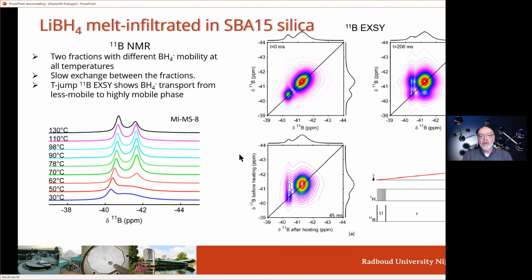Okay, so we also did two-dimensional NMR, and now I revisit the boron spectrum of the BH4 unit again. And there we can see in a so-called exchange spectrum that when we do such an experiment, we can correlate the boron shifts in 1 dimension to the boron shift sometime later. If there is no time in between, of course, nothing happens, and we see the signal on the diagonal of this 2D spectrum. However, if we allow a certain time between these periods, we get a spectrum with so-called cross peaks.